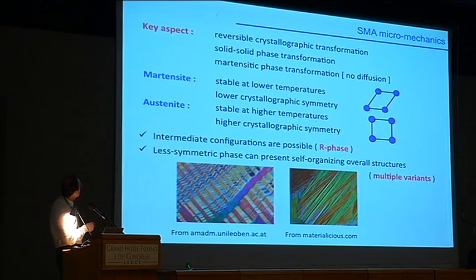So the martensite is a phase which is stable at lower temperature, and in general is characterized by a low crystallographic symmetry. The austenite instead is a phase which is stable at a higher temperature and is characterized by higher crystallographic symmetry. So here I indicated a square for the higher-symmetry austenite, and this skew element for the lower crystallographic symmetry of the martensite. And basically, understanding that the material can go back and forth between these two solid phases, you can really understand what's going on inside the material.